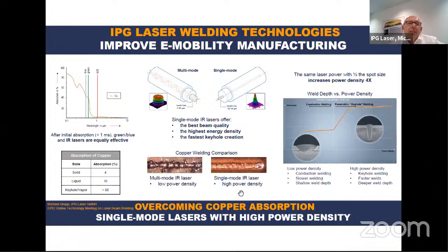And for example, on the right side, we can see that if we reduce the spot size to the half, we increase the power density 4 times. This is just the area of the spot on which we can apply this power. So the single mode lasers today we have in a range of a few watts up to several kilowatts. Typically applied in e-mobility, we are somewhere in the range between 500 watts and 3 kilowatts most of the time. And this is the right power density and the right power to create very stable processes. So we can create keyhole depths of a few tenths of millimeters up to a few millimeters, 3 to 4 millimeters. Next slide, please.